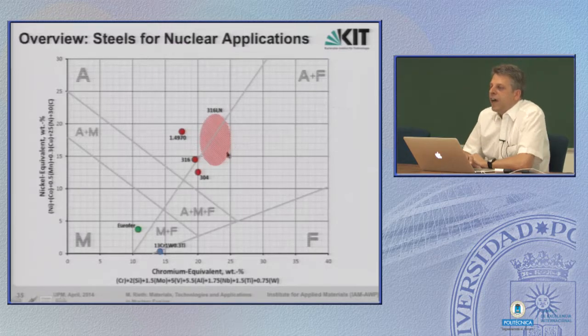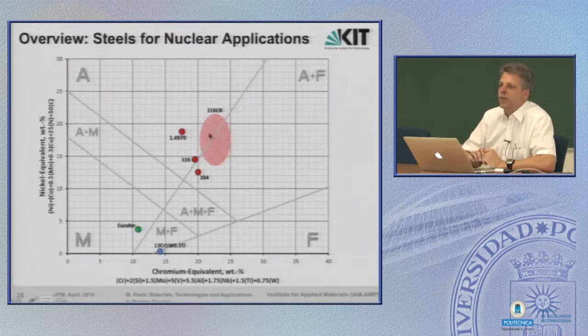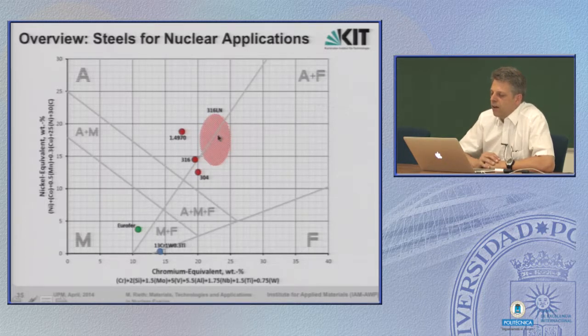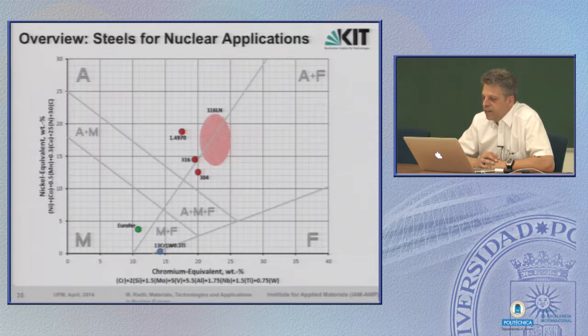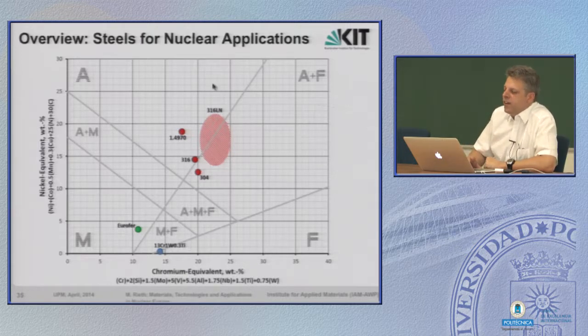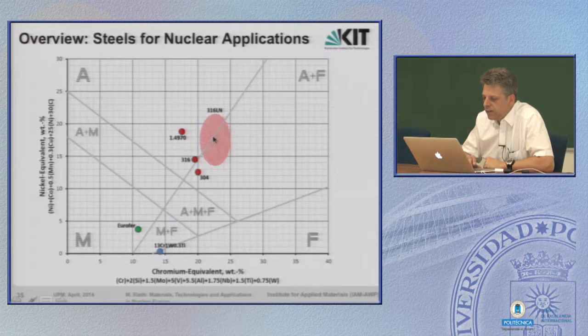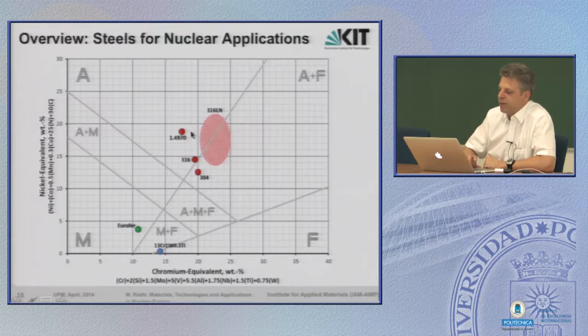Here is where we end up with 316 steel. 316 steel comes with a variety of different composition ranges, so this field here produces 316 austenitic steels, and you see that depending on the specific mixture, it is more or less on the border between austenite and ferrite. This has a reason, but again, these are very specific topics.